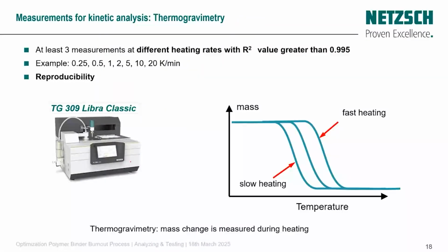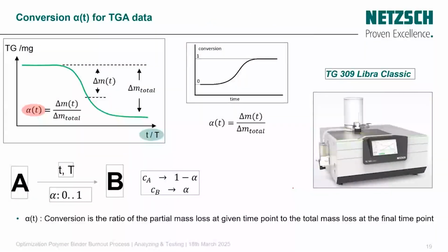So what kind of data do we need? Basically, we need at least 3 measurements at different heating rates with the R-square value greater than 0.995. If the value is less than 0.995, in this case, we always advise the customer to do more heating rates in order to improve the accuracy of the model. It's also important to have reproducibility of the result, so we need to repeat the same measurement under identical conditions to ensure that we can get the same result. And we use thermogravimetric analysis, which gives us an idea about the change in the mass of the sample as a function of time.